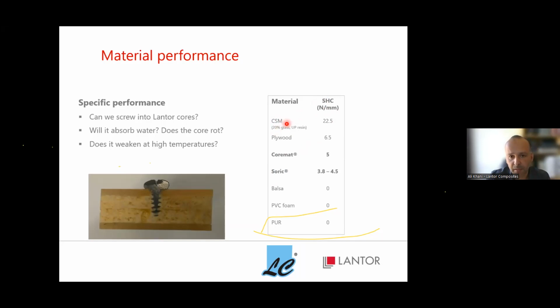You can see for the CSM chopped strand mat glass, 20% glass, this value is the highest, 22 Newton per millimeter. Then you have the plywood, and after that the Coremat and Soric. And then balsa, PVC foam, and polyurethane foam basically cannot have any screw retention. Will it absorb water? We do tests for our type approval, and we test our cores. We place the laminates we make in a water bath for 28 days at 35 degrees, and we measure the mechanical properties afterwards. This should not drop, and we see that it has not dropped.